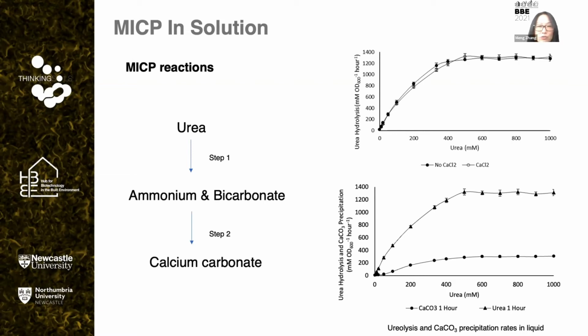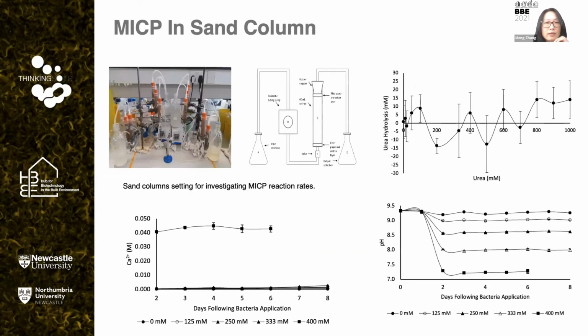And our figures show that when we have a fixed concentration of calcium ions in the system, the urea hydrolysis rate does not have a linear relationship with the rate of calcium carbonate precipitation. Although this scenario has been commonly assumed as the condition for many computational model validation studies.